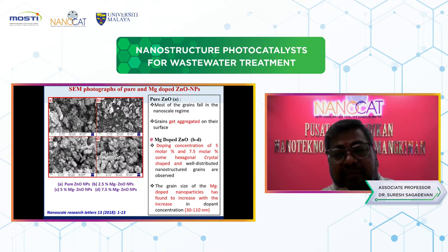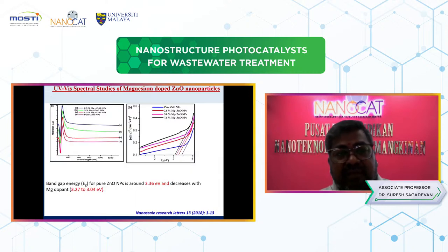It looks like a hexagonal, very clear surface morphology of hexagonal crystal structure, and well distributed nanostructure grains are observed. The grain size of the magnesium doped nanoparticle was found to increase with the increase in dopant concentration, in the range of 30 to 110 nanometer. As well, we studied the optical properties. We observed the maximum absorption using the absorption spectra, and we calculated the band gap value using the Tauc plot. The band gap energy for pure zinc oxide nanoparticles is around 3.36 electron volt, but it decreases with magnesium dopant from 3.27 to 3.04 electron volt.